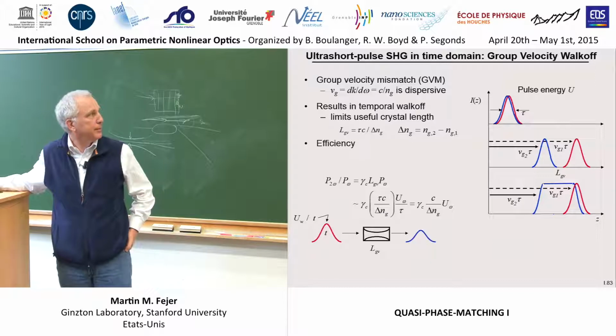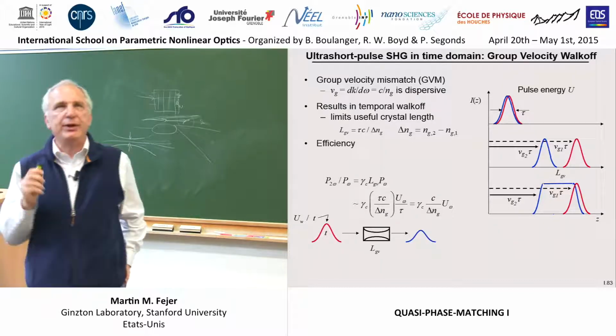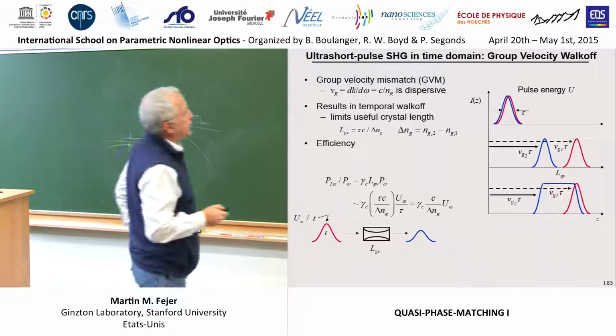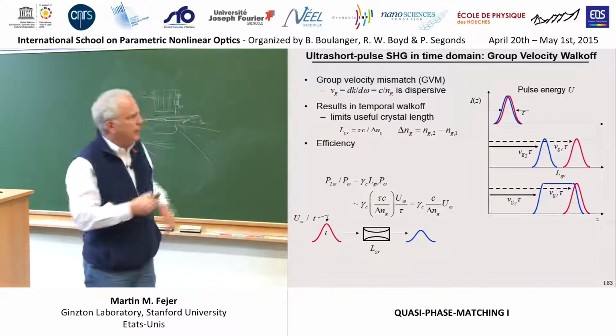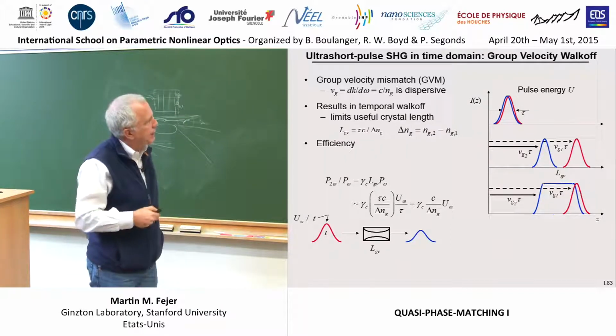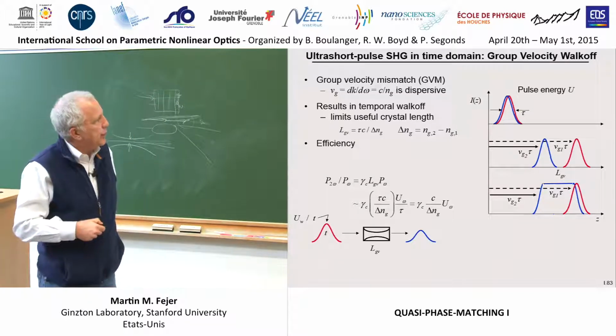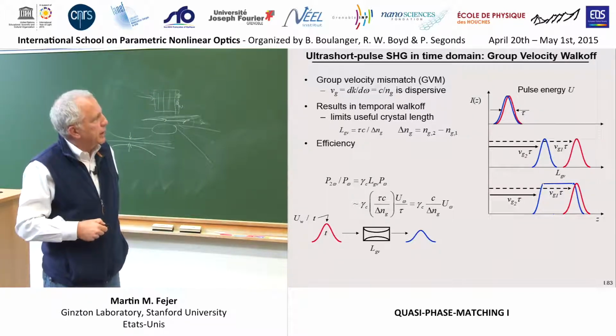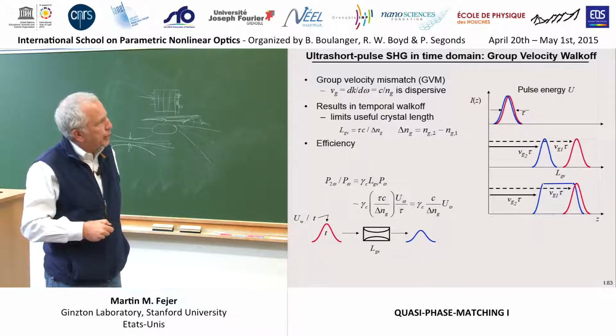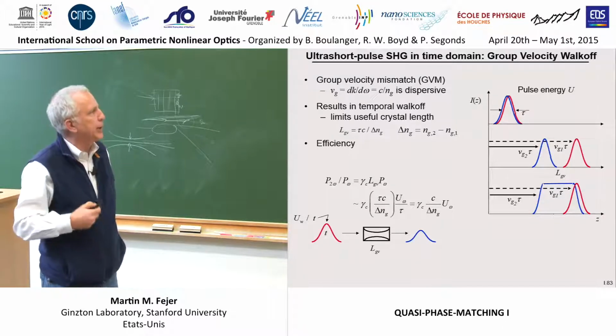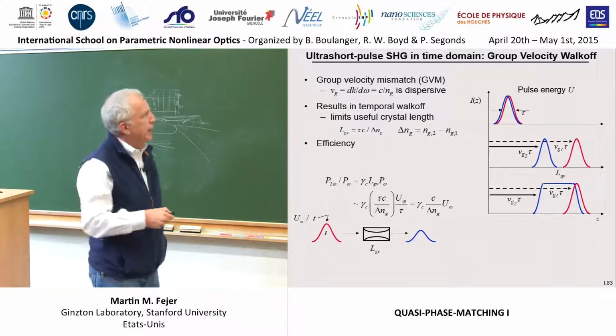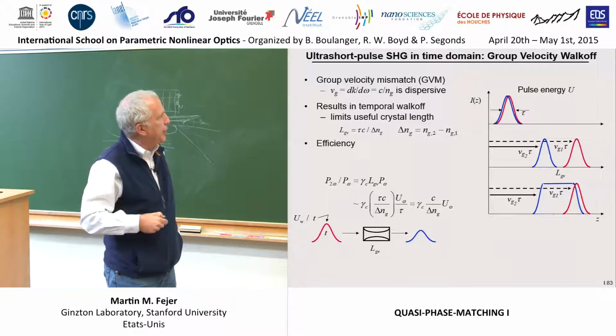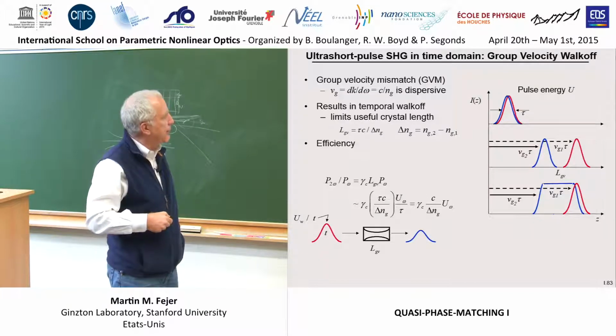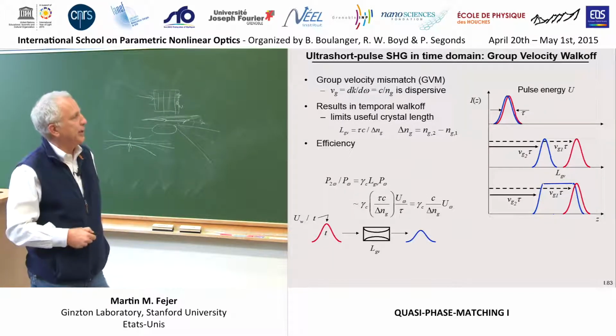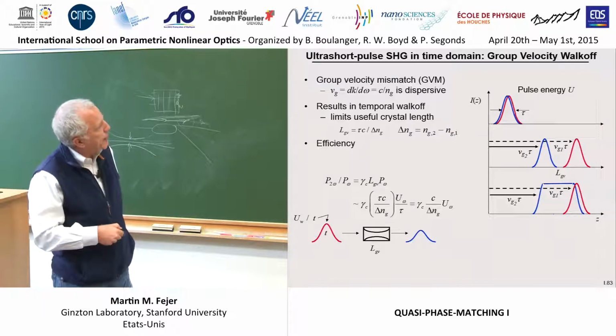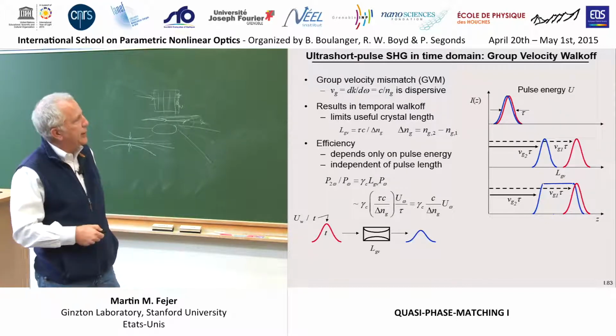So if you look at the efficiency of a nonlinear mixing process in such a situation, if you've confocally focused it and all that kind of stuff that, again, we've heard about already, we know that the second harmonic conversion efficiency is proportional to the length of the medium and proportional to the power in the pump. So in our pulse situation, the power in the pump could be viewed as the energy in the pump divided by tau. Pulse energy divided by pulse duration.